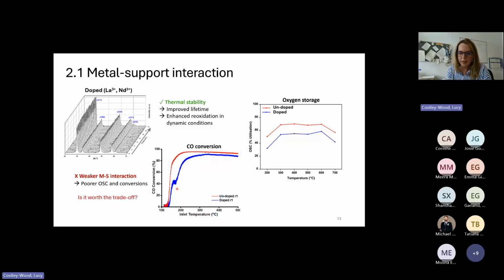Is it worth the trade-off then, if we're sacrificing performance and oxygen storage? Well, another part of the project was aging the catalysts. And if we just look at what happens to the oxygen storage after aging, the blue is the doped material, which after 12 hours at 950 degrees retains all of its high temperature oxygen storage ability, whereas the undoped material loses it across all regimes. So yes, the trade-off is still worth it, simply for the lifetime of the catalysts.